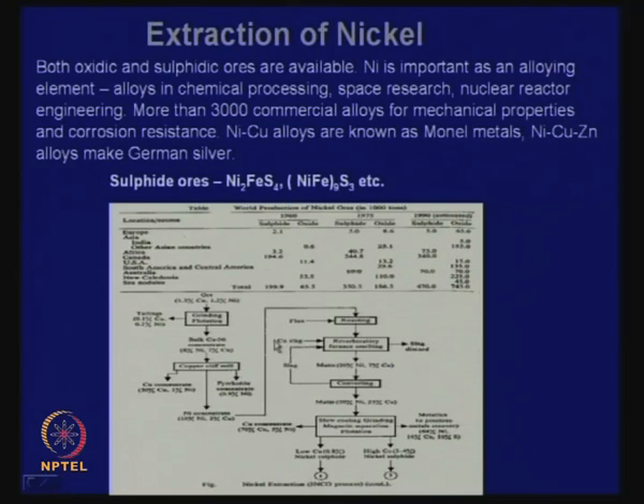If somewhere there is a copper slag available, that can go in here, because we need in the matte copper also. So, nickel sulfide processing also involves a matte, which is a mixture of sulfides containing 20% nickel, 7% copper. It will undergo converting, exactly like in the case of copper. The slag will go back to the reverberatory furnace. In converting, we will have matte with 50% nickel, 25% copper. There is a slight difference here. In the case of copper converting, straightaway we are producing blister copper. In this case, we do not do that. We produce a product which goes for slow cooling, grinding and magnetic separation to finally get a low copper nickel sulfide and high copper nickel sulfide.